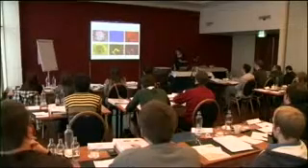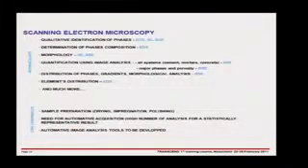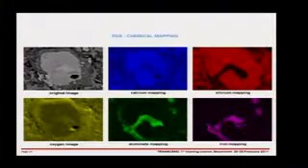Here we can see the distribution of alumina. Alumina is in the ferrite phase, but it's higher in the C3A phase, and so on and so forth. This is much more useful when you want to look at a kind of degradation reaction. For example, you want to look at sulfur coming into a sample, or calcium being leached out of a sample.